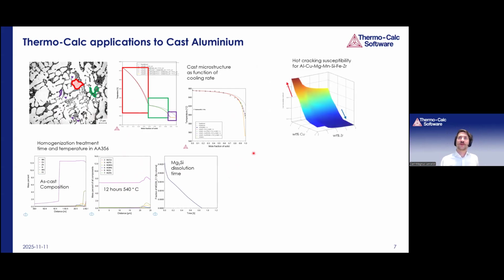And also very important to cast alloys is the hot cracking or hot tearing susceptibility. We have a model in the software for this. There are different kinds of models that you can select, but we can calculate this as a function of different chemistries. In this example, we have a multi-component alloy with many different impurity elements, and we are varying the copper and zirconium content to see how the alloying is lowering the hot cracking susceptibility.